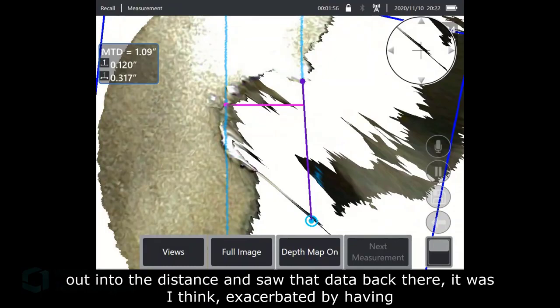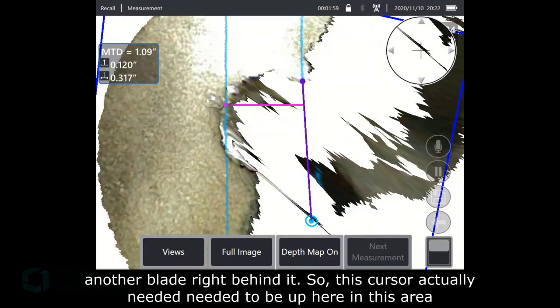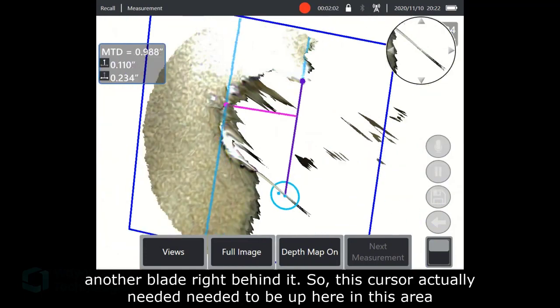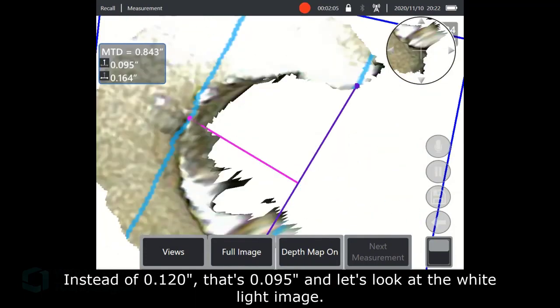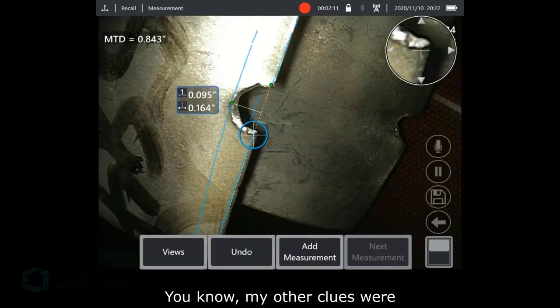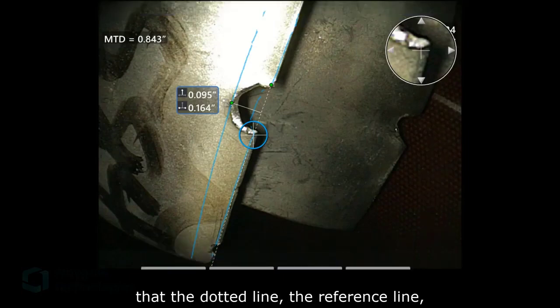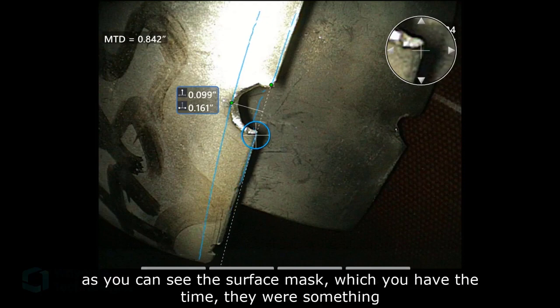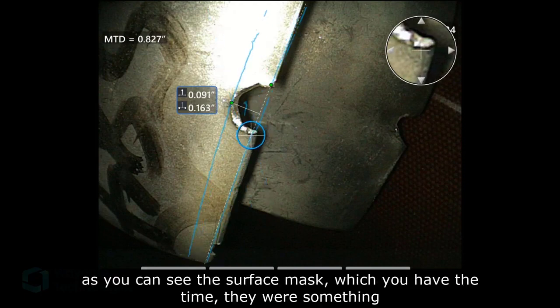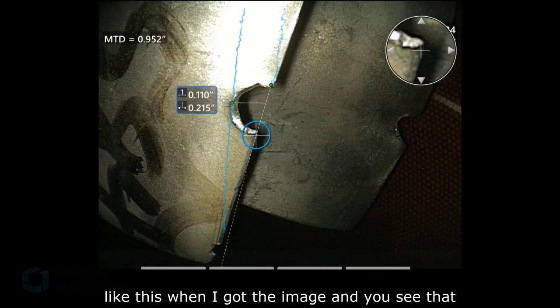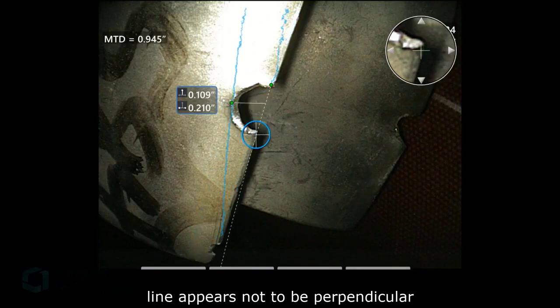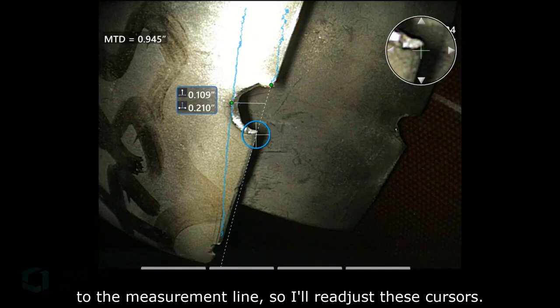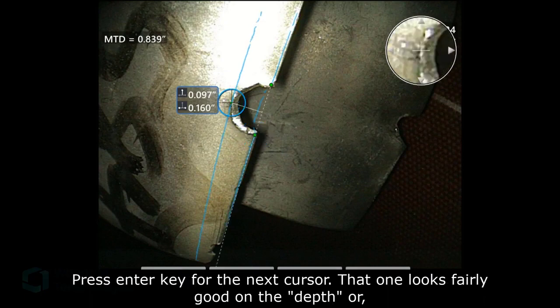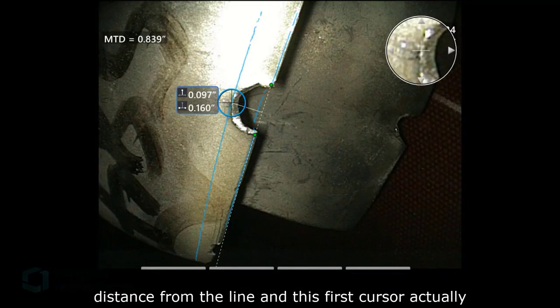It was, I think, exacerbated by having another blade right behind it. But this cursor actually needed to be up here in this area. So instead of 120 thousandths, that's 95, but let's look at the white light image. You know, my other clues were that the dotted line, the reference line, and you see the surface mask, which he didn't have at the time, they were something like this when I got the image, and you see that line that appears not to be perpendicular to the measurement line. So I'll readjust these cursors, press the enter key for the next cursor. That one looks fairly good on that depth or distance from the line.